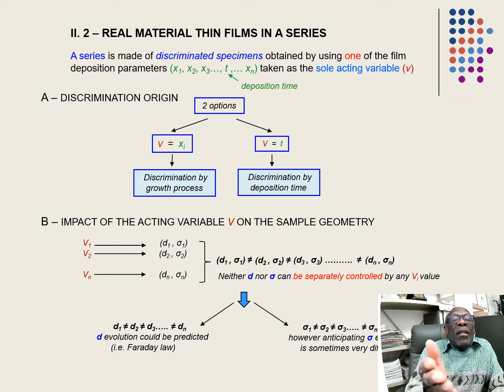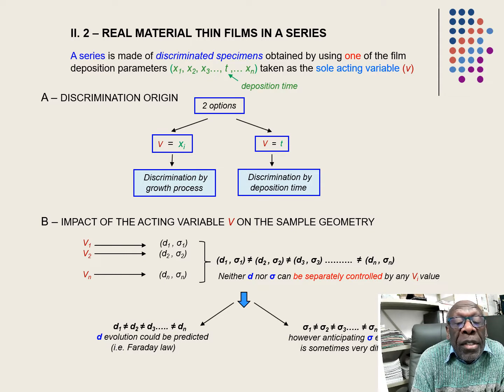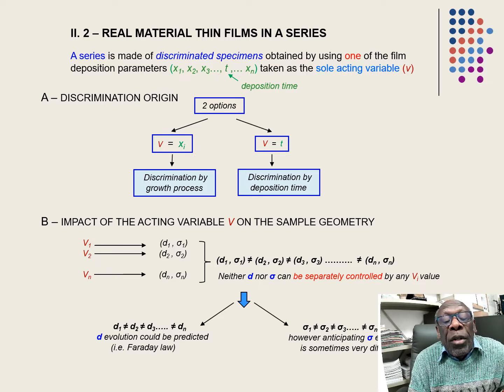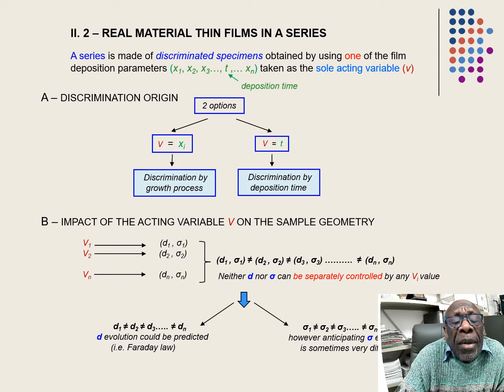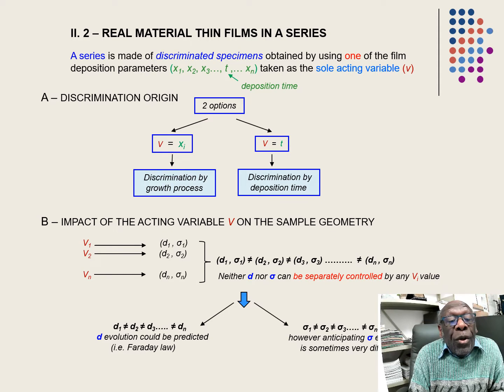if you vary the different samples by having a variable in your deposition process, you will always have different values of the couple, D1, sigma 1, etc., different to D2, sigma 2, etc. Always a couple, because you cannot separate D and sigma. You cannot see the evolution of D or sigma in a separate way. They are connected. In general, the differences between the D values are more noticeable. However, anticipating the evolution of sigma values is sometimes very difficult. So, if you have the presence of the two geometrical characteristics, it's very difficult to study the property evolution of your samples in a simple way.